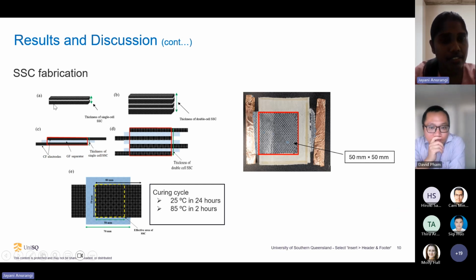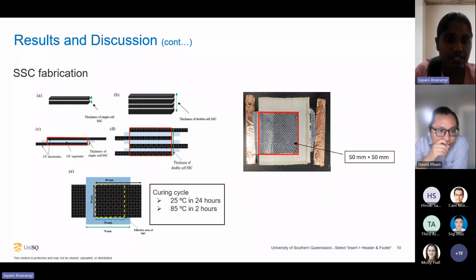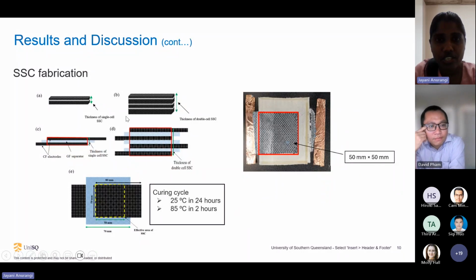In the single cell structural supercapacitor, I use two carbon fiber electrodes and two layers of glass fiber separator. Actually, I use two layers of glass fiber separator to avoid the short circuit of the electrodes during the charging cycles. After curing, on the right side it shows the double cell structural supercapacitor. Here I have used 4 electrodes and 6 layers of glass fiber separators.